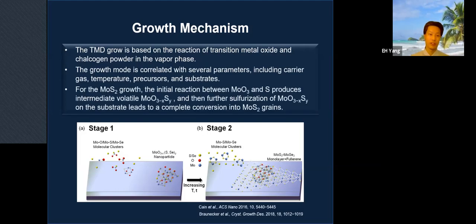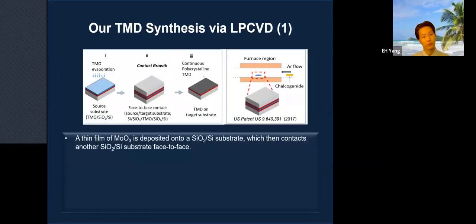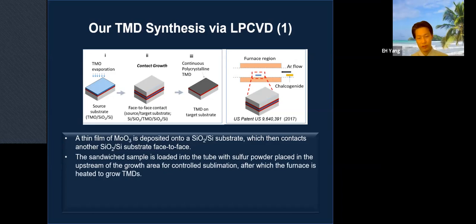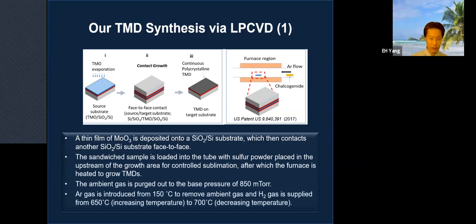Specifically for the moly disulfide growth, the initial reaction between moly trioxide and sulfur produces intermediate volatile suboxides. Further sulfurization of these suboxides on the substrate leads to a complete conversion into moly disulfide grains. To do this, you put a thin film of moly trioxide onto the substrate, then contact another substrate face to face. Then the sample is loaded into the tube with sulfur powder placed upstream of the growth area for controlled sublimation. Then you purge the tube and put in argon gas and hydrogen gas at the right temperature, right time.